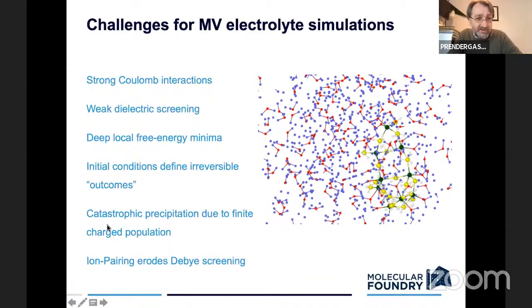And in some horrible cases, you may just have precipitation for multiple reasons, but one is that you have a finite population of charged species, so they'll try to find each other. And as they do, you will be removing the mechanism by which they screen each other. So Debye screening, which comes from the free charges in the solution, if they start pairing up, and you only have n of them in your box, then every time they pair up, you lose 2 free charges. And so your Debye screening goes down, and now they see each other even more, and it cascades. And so you basically end up with these precipitates in your solution. Whether that's real or not, you have to question based on your knowledge of the physics of how they might stay apart in the first place through screening.